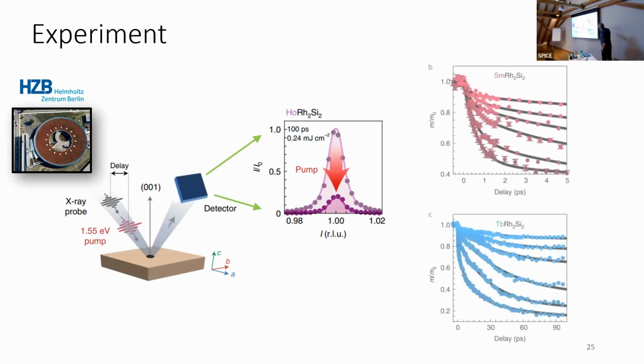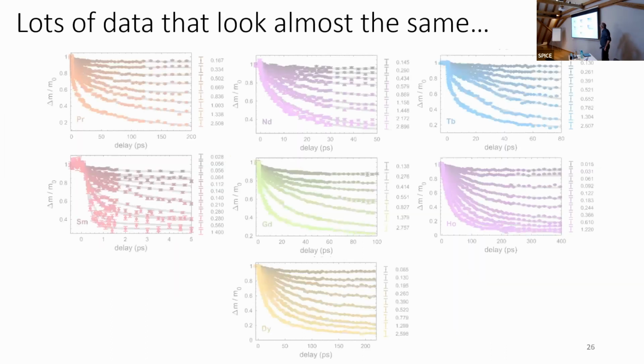Here are two examples. This is samarium rhodium-2 silicon-2. This is terbium rhodium-2 silicon-2. You can definitely see that there's a difference in amplitudes and in time scales. This is 5 picoseconds. This is 100. These are differences that appear. In fact, we collected a ridiculously large amount of data on all of these materials.